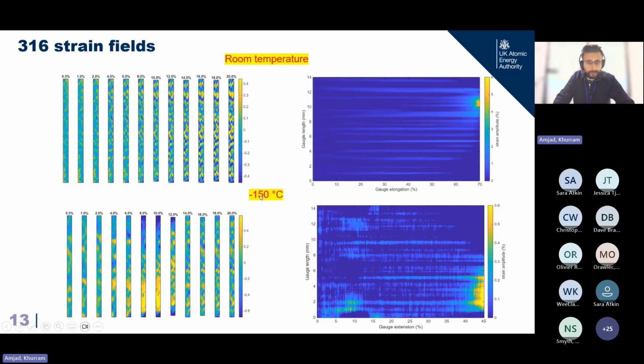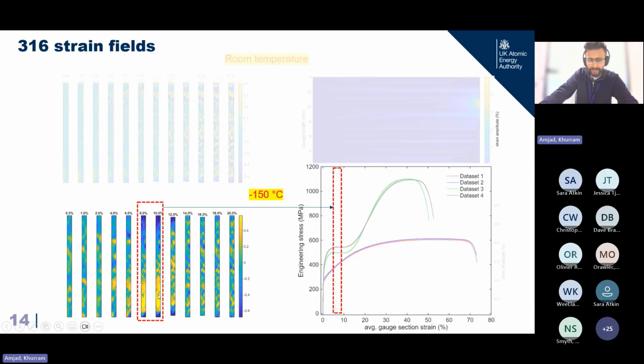At the bottom, we have similar strain maps and the evolution of the strain field at minus 150 degrees centigrade. What is interesting in these is that at about 8 to 10% for this particular sample, we see a strain localization very similar to what we see in necking. This corresponds to that plastic flow region that we see. So it is like necking happening here before the martensite transformation kicks in, which causes again a more spatially dispersed heterogeneity. I believe this is the first time DIC has been able to pick up this phenomenon, even though this curve is well characterized in the literature. We can visually see exactly what happens at this plastic flow region: it creates a necking point prior to actual failure of the sample.